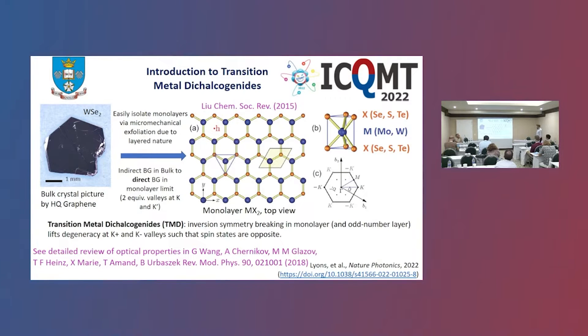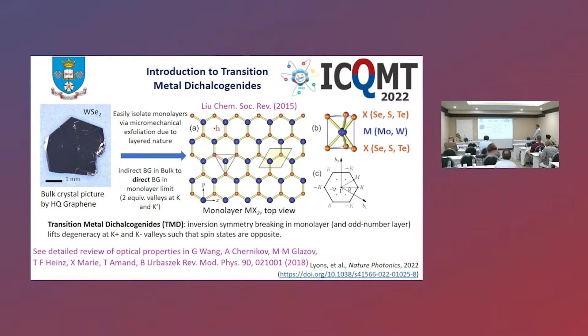From an optics perspective, we see that the bandgap goes from an indirect bandgap in bulk and switches to a direct bandgap in the monolayer limit. This is formed at two equivalent valleys at K and K-prime in the Brillouin zone. Thanks to the inversion symmetry breaking in the monolayer, this lifts the degeneracy at the K and K-prime valleys, such that the spin states in these two valleys are opposite.